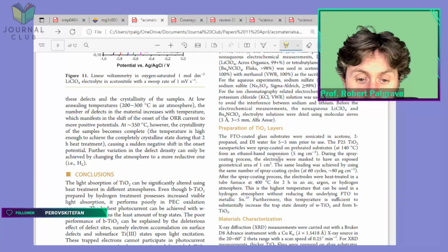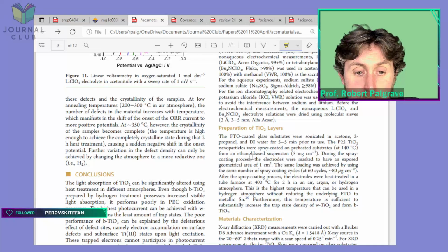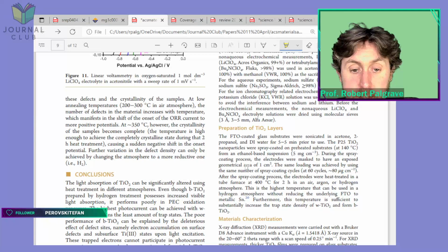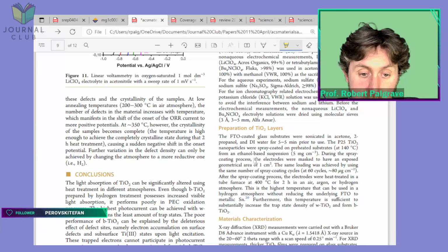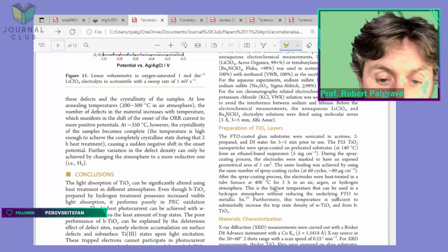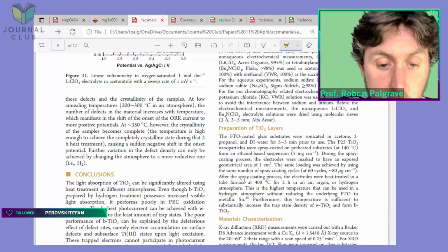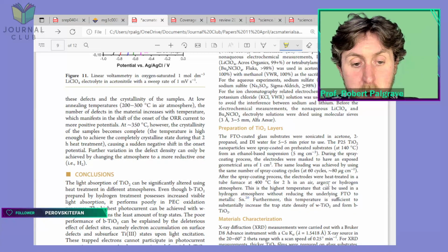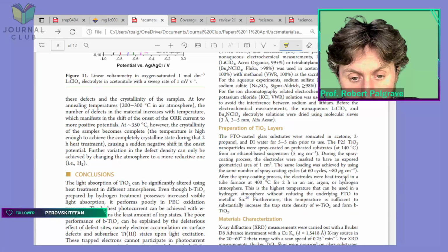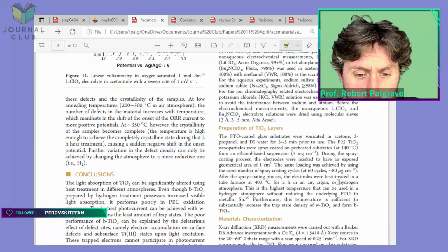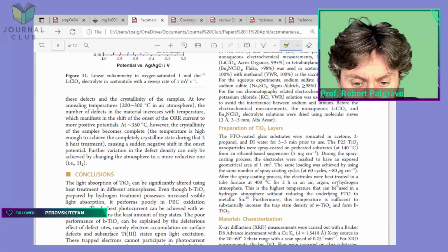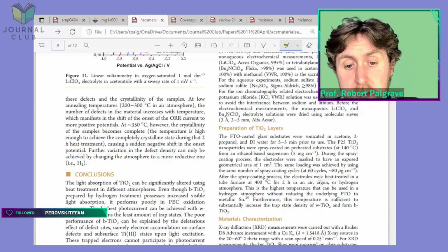During the spray coating process, the electrodes were masked to have an exposed geometrical area of 1 centimeter square. The same loading is achieved by using the same number of spray coating cycles. Okay, so they put 18 micrograms per cycle. They did that 60 times. After the spray coating process, the electrodes are heat treated in a tube furnace at 400 degrees for 2 hours in air, argon, or hydrogen atmosphere. Okay, is it pure hydrogen? They don't mention whether it's pure hydrogen or not. But this is their methodology.